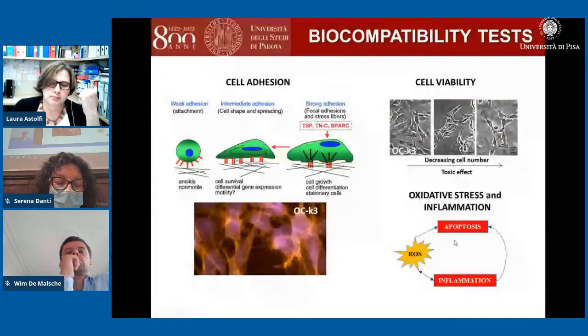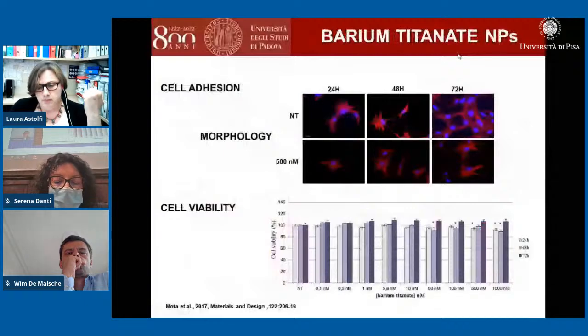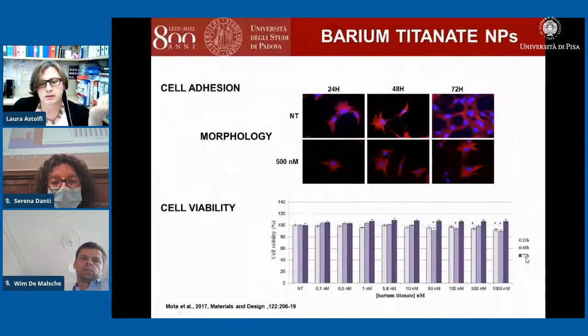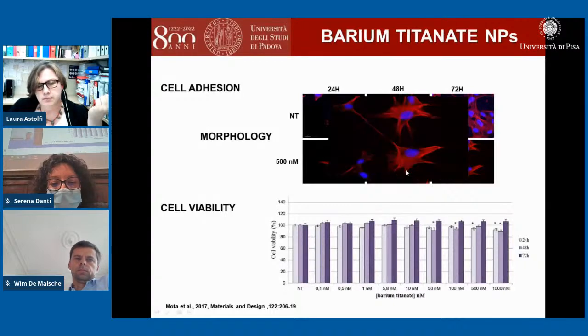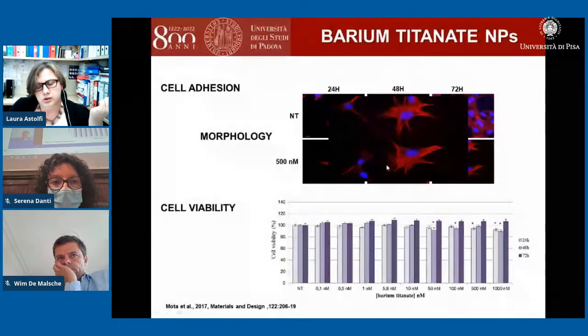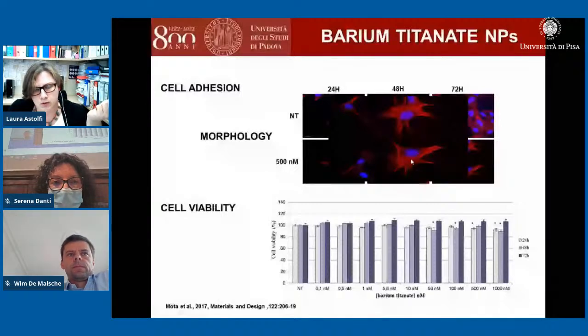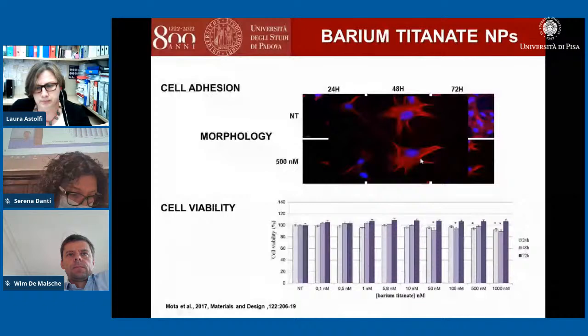About the barium titanate, the cell viability assay shows that it is never toxic, even after 72 hours. And about the cell adhesion, so the morphology, after 72 hours at the highest amount that we tested, we found that the cytoskeleton is still well organized. The cells have the typical polygonal shape, and the nuclei are rounded with good diffusion of the chromatin. So they are in healthy condition.